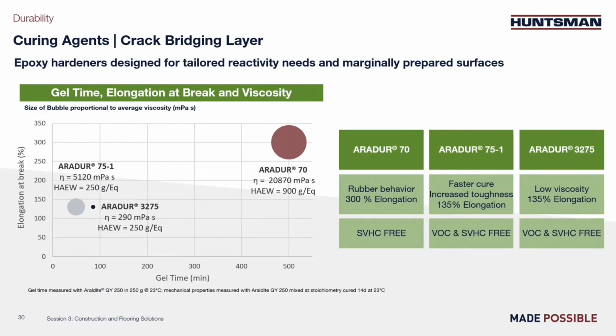Here on the scheme, or the graph more, you can see the three products discussed before. And on the x-axis, you can see the gel time, and on the y-axis, the elongation at break. The size of the bubble is proportional to the viscosity. If Aradur 70 gives up to 300% elongation, the viscosity is high and the reactivity extremely low. So the two other products, Aradur 75-1 and Aradur 3275, are still giving a good elongation at break around 130%, while reactivity is more in an acceptable range.